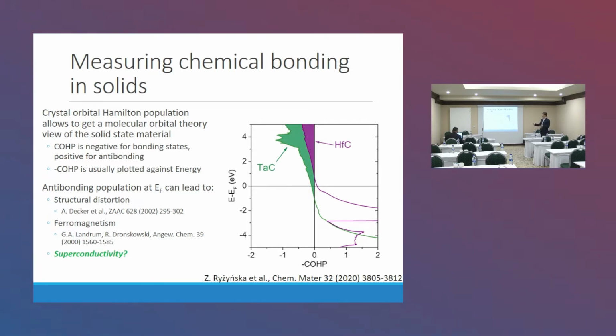The COHP is negative for bonding states because the energy is negative for the bonding state. So we usually plot negative COHP and then it's going to be positive for bonding states. We usually plot it against the energy. It can also be plotted in a k-resolved case if needed, right?